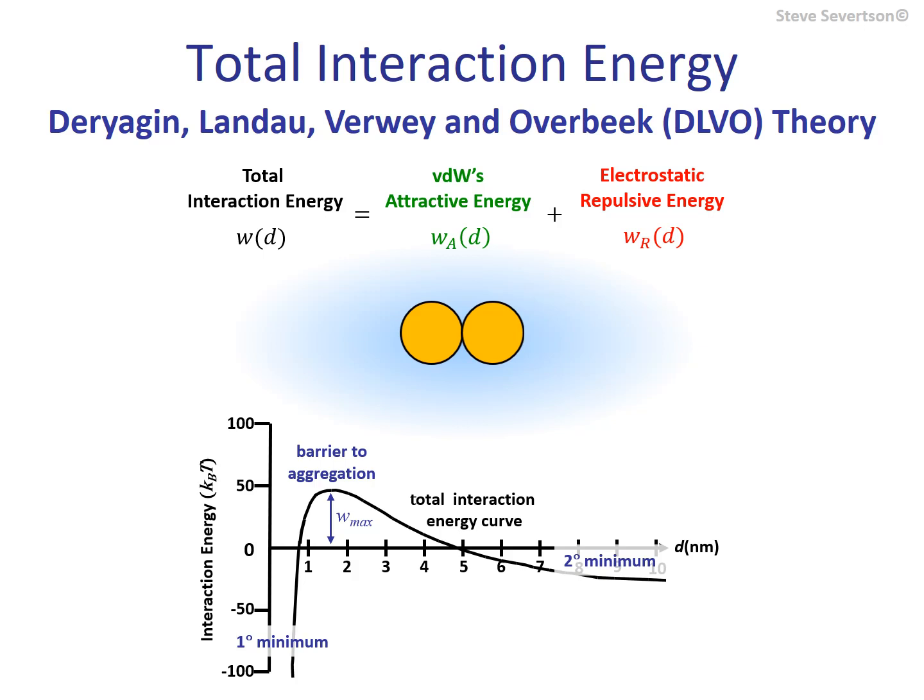On average, particles moving in a colloid possess about 1.5 kBT of energy. Thus, a barrier of just a few kBT should be sufficient to stem primary aggregation. However, it is important to emphasize that this is an average, and there are particles with kinetic energies higher than this, and convective motion further increases this population. A good rule of thumb is that a barrier of maybe 15 to 25 kBT provides for good kinetic stability.